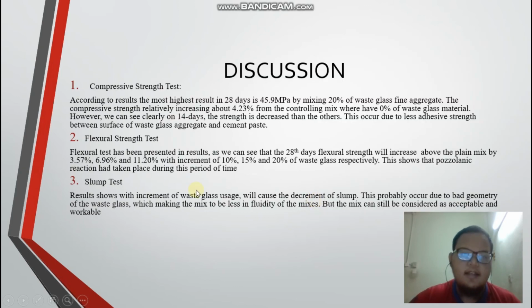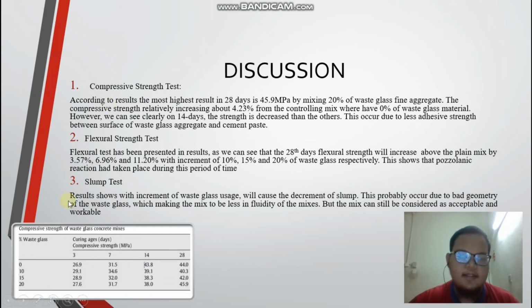In the discussion of the compressive strength test, according to the results, the highest result at 28 days is 45.9 megapascal by mixing 20% waste glass as fine aggregate. The compressive strength relatively increased about 4.23% from the control mix. However, as you can see, at 14 days it decreased from the others. This might occur due to less adhesive strength between the surface of the waste glass aggregate and the cement paste.